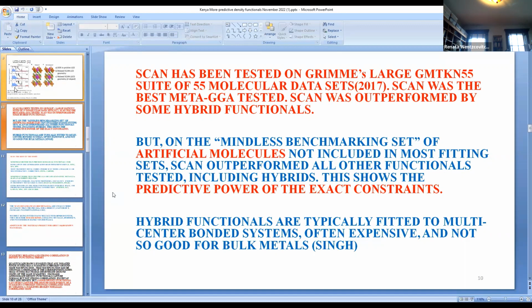So the interesting thing about this set is that none of these artificial molecules have ever been included in the fitting of standard functionals. And on that set, SCAN outperformed all the other functionals that were tested, including the hybrid functionals. To me, this shows the predictive power of the exact constraints. If you have a functional that satisfies many exact constraints, it can not only describe familiar systems, but even unfamiliar and unusual systems.